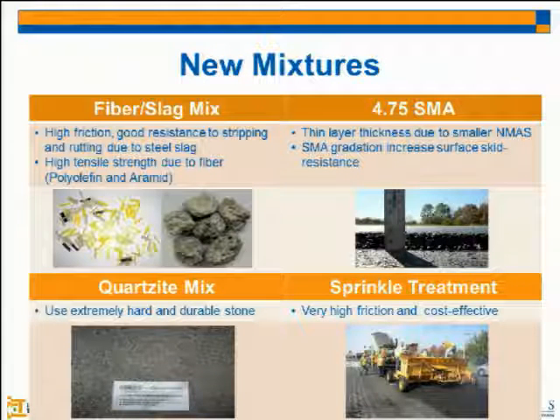Here are the four new mixtures. The first one is a fiber slag mix. We use the steel slag for this mixture to reduce the material cost. Because of using the steel slag, we expect high friction and good resistance to stripping and rutting. And by adding the fiber, we were expecting higher tensile strength, because the fiber holds the materials. So when we have reflective cracking or this kind of cracking, the fiber holds the materials.